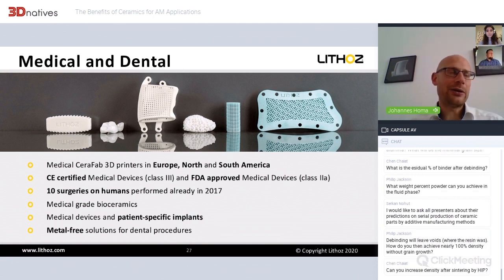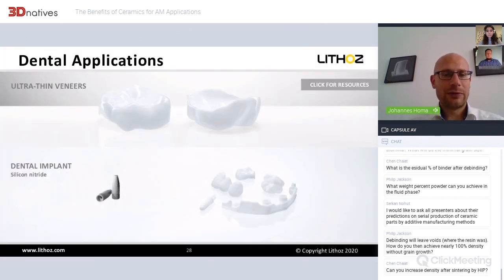As I said, there is a clear trend, at least in dental, from metals to ceramics. And to get a little bit into dental applications, ceramics is very well established in dental, and we see for ceramics a good advantage, especially with ultra thin veneers or with dental implants out of silicon nitride or of other materials. So there are a couple of applications where we see that conventional forming is not performing very well, and where there's a technology gap, and additive manufacturing could fit in here very well.